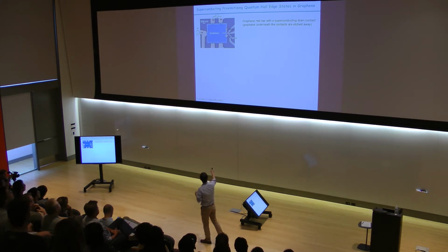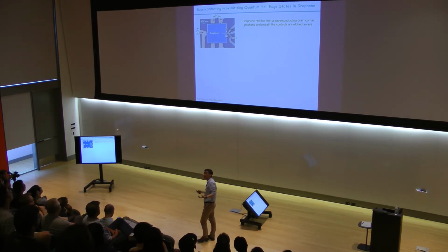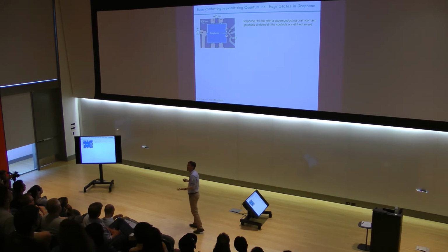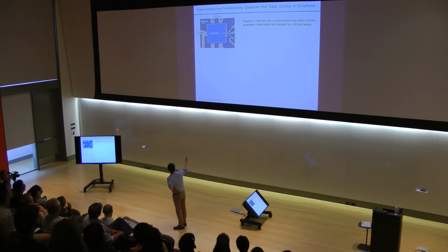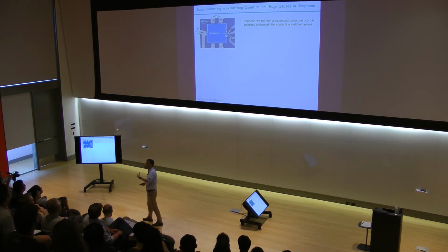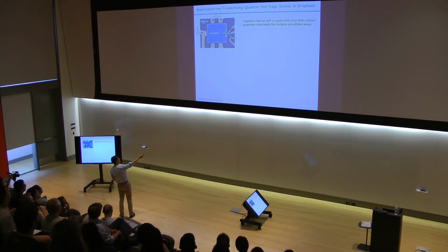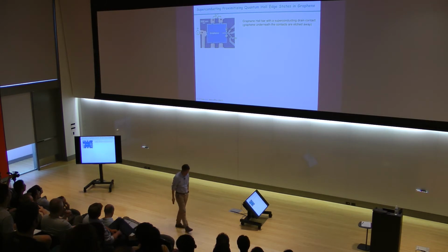Indeed, in this experiment, we made a very narrow, finger-like electrode onto the graphene channel and applied the magnetic field. Under the magnetic field, once the Landau levels form and everything is quantized, the transport is carried only by these edge states. And simply by measuring the edge state potentials, one knows how the quantization is happening. So basically, we did a very similar experiment to the typical quantum Hall measurement, except that one of the electrodes is replaced by niobium nitride, which is known to be a type 2 superconductor, where the Hc2 is large enough that when you have the quantum Hall effect, the superconductivity can still be preserved.